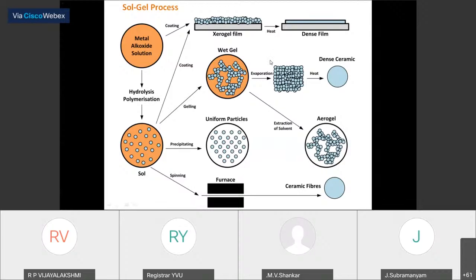The gel is formed, so we can transfer it to the required shape or size depending on your requirement. Like that, we can form different varieties of things by using sol-gel. This is not possible in the chemical precipitation method, where we get only the precipitate, that is, the nanoparticles. But in the sol-gel process, we can coat the gel at any place, so we can use it for the required dimension and shape. We can get thin films, pellets, powders, or particles. Whatever form you want, you can get it by using the sol-gel method.